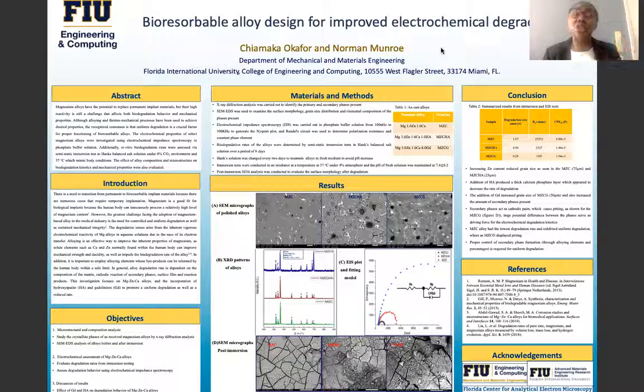Alloying is an effective way for improving the biodegradation behavior of magnesium alloys, and it is important that we alloy with elements such as calcium and zinc, which do not pose any threats to the human body. As we all know, there are over-the-counter drugs of zinc and calcium. In this investigation, we look at magnesium zinc calcium alloys, and we incorporate hydroxyapatite and gadolinium elements to see how they affect the degradation behavior.